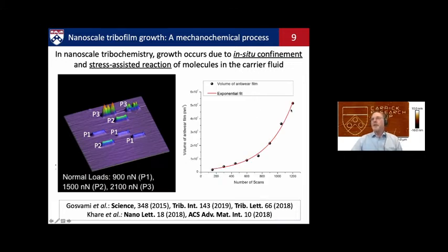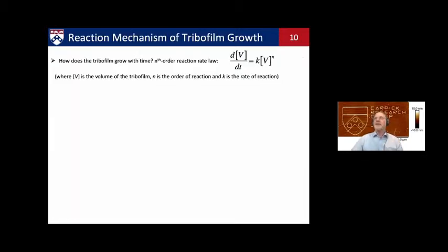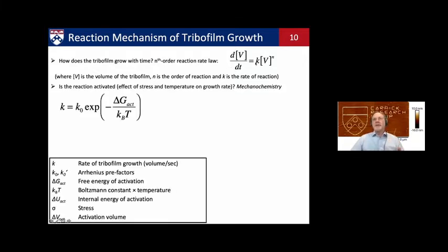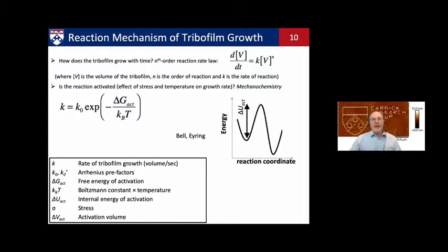And you can track the growth by periodically measuring the height and width of these films. You can track the volume of the film as a function of the number of scans. So this is just one example of many. We do these experiments at different stresses, different temperatures, and we track this rate of growth. And from that, we can get a reaction rate. Okay? And if a reaction follows Arrhenius kinetics, then you expect that reaction rate to vary exponentially with the free energy of whatever the barrier is to this reaction. Now, Bell and Eyring showed how force or stress can affect the energy barrier to such reactions through this framework of mechanochemistry.